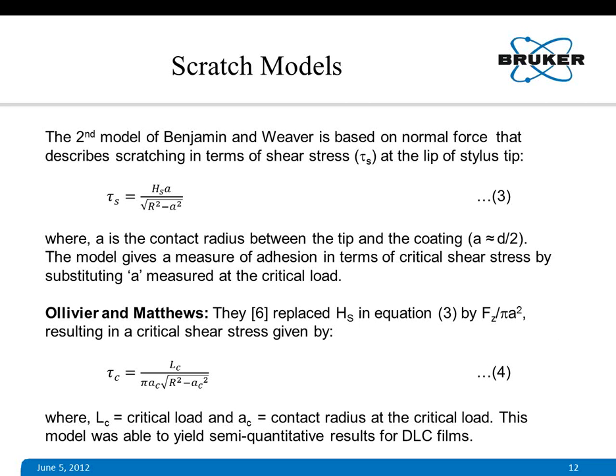The second model Benjamin and Weaver proposed was based on normal force, and equation 3 expresses the shear stress at the lip of the stylus tip in terms of hardness and the contact radius between the tip and the coating, A, which is basically half of the scratch width. So this model gives a measure of adhesion in terms of critical shear stress by substituting A measured at the critical load.